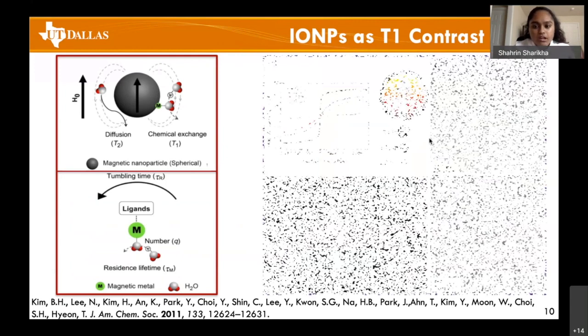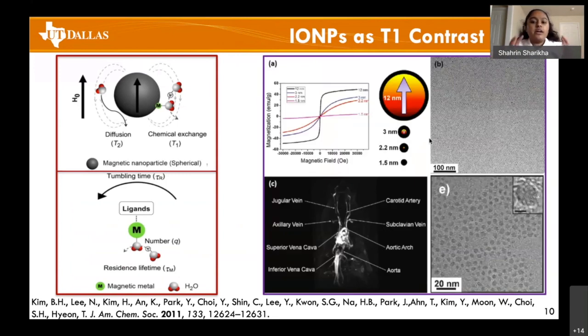Now, iron oxide nanoparticles can be viewed as a core structure surrounded by a shell. And the core is highly magnetized, so is the shell. But the thing with the shell is that it exhibits something called spin canting, where all of the magnetizations on the surface itself aren't properly aligned. They're all random, whereas the core aligns with the magnetic field.